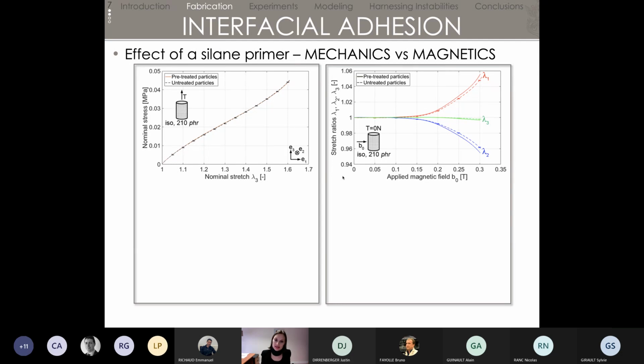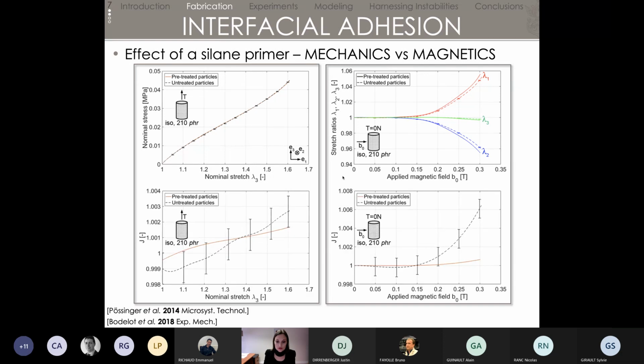Now you take that same sample, put it under a magnetic field and maintain the force at 0, which means it's just deformation that's induced by the magnetic field. And you look at how much it deforms. You see that we have different responses when the particles are treated or non-treated. We confirm that in another way, which is by plotting the Jacobian of the transformation. For the purely mechanical test, bottom left, you remain around 1, so you have an incompressible behavior.